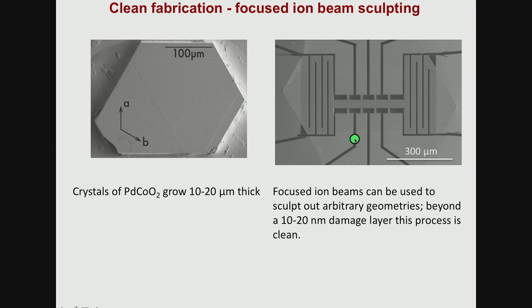So what we've created there, or what Nabhanila and Andy created, is current injection through a special meander, for technical reasons, into a bar, a channel of a defined width. We have 8 voltage contacts on that channel, so we can do multi-contact measurements, both of the magnetoresistance if we apply a field and of the Hall effect. But the point's a general one. It's really now technically becoming feasible to do experiments on interesting materials in ways that were impossible even 10 years ago, and that's a great development.